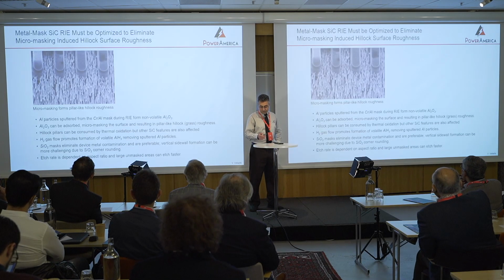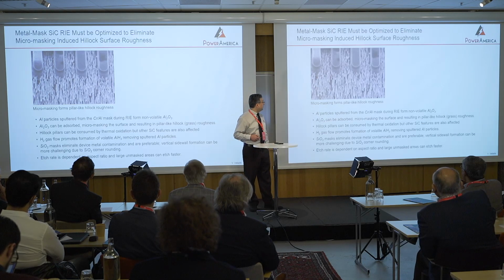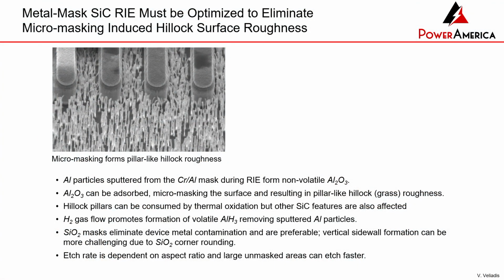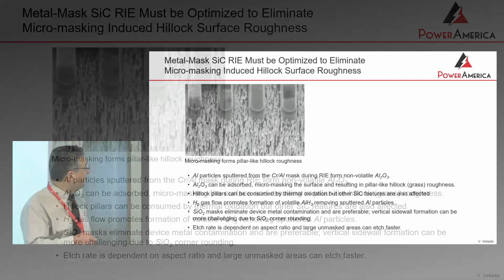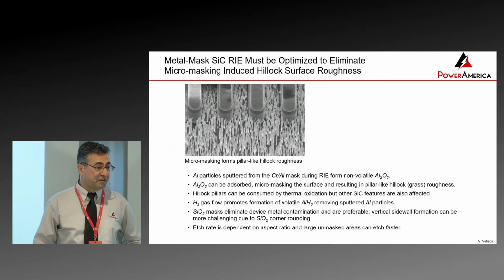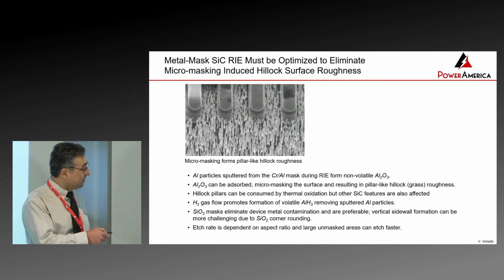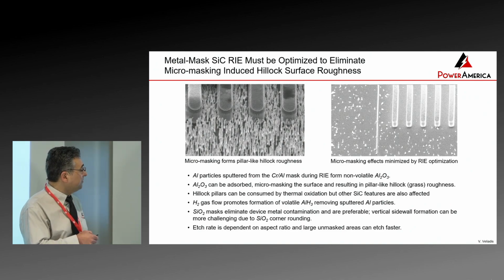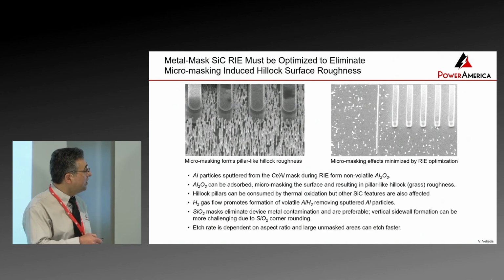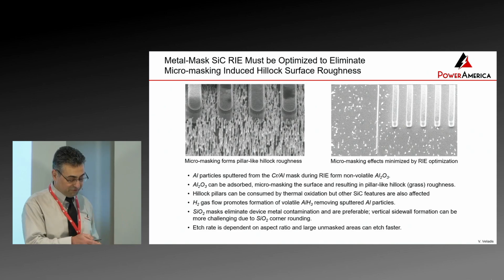Okay, so some examples of my old work and shortcomings. You can see here I'm trying to make vertical pillars, 0.7 microns. I put a metal mask because you cannot use resist. The selectivity is bad. The metal mask, as I do the RIE, creates this little microtrenching issue, which is called grass, highly undesirable. So what I did next, I said, okay, let me heat this up and eat those little silicon carbide pillars away. It kind of helped, but it also shrank the size of my pillars, right? That's not a good way to do it.